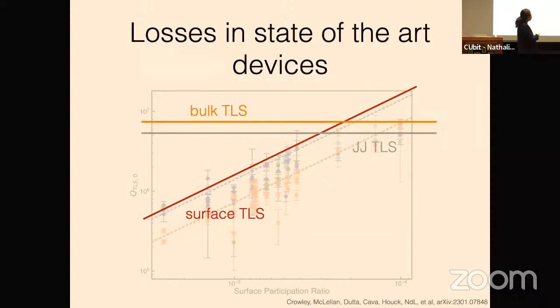And what this allows you to do is disentangle where are my losses. And what this tells you is that if you thought that you were living in a world where it was all surface TLSs, and then you just did a bunch of random things to the surface and then tried to measure devices, you would have failed, right? Because up here, you would have found that you were just bulk limited, but not 100% bulk limited. Up here, you sort of have equal contributions from the surface and the bulk, so it would have been very hard to detect.